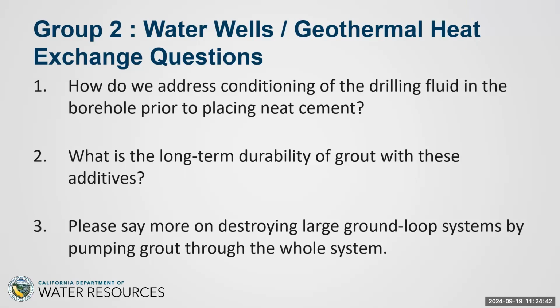I think you put your finger on it there, because even a contaminated drill slurry, what do you think the density is going to be? Maybe 80, 90 pounds cubic foot? I'm a pounds per gallon type of guy. Yeah, okay, go ahead then. But yeah, I would estimate that in this case it was above 9.8, probably approaching 10 pounds per gallon, and probably a viscosity over 60. Okay, so 10 pounds a gallon. Well, the grout is still going to be denser than that.